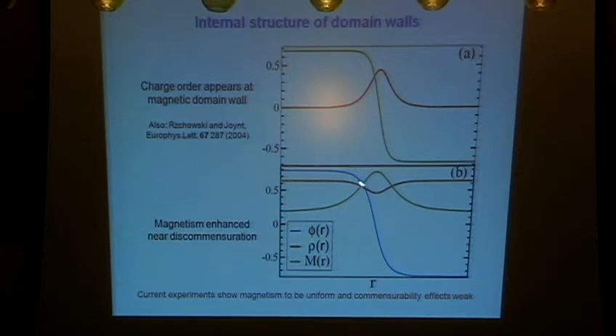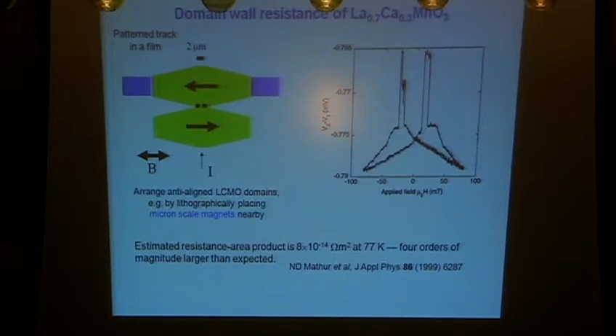Or if I have a magnetic domain wall, at the magnetic domain wall, it provides a soft spot where charge order tends to be enhanced. And that latter one, for example, might explain things which are periodically reported, although are very difficult to nail down,